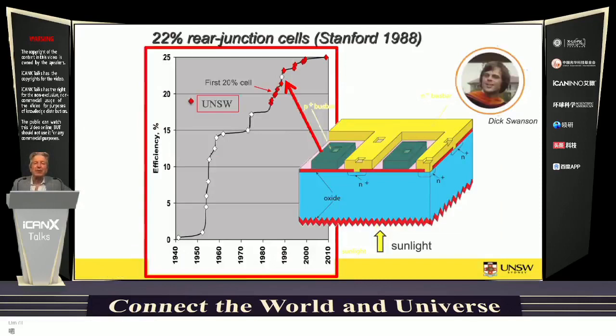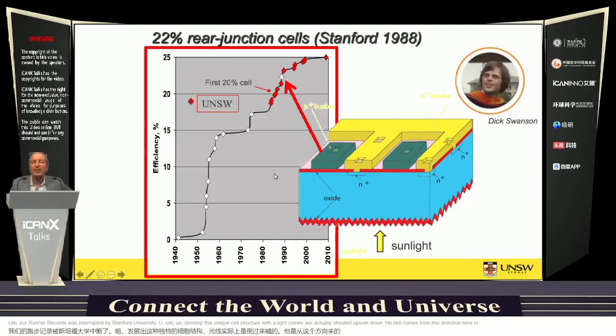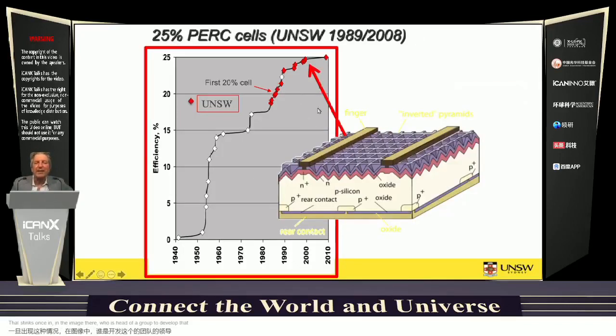Our run of records was interrupted by Stanford University, who developed this unique cell structure where the light comes, I've actually shown it upside down here, light comes from this direction here, and all the contacts are on the rear. That's Dick Swanson in the image there, who was head of the group to develop that. That encouraged us to put the PERC cell into, to get it fully developed. So we re-established the world record quickly using the PERC cell and maintained it right through till 2014 using that structure, reaching 25% efficiency. So you can see the structure on the rear here that I'd sketched earlier.